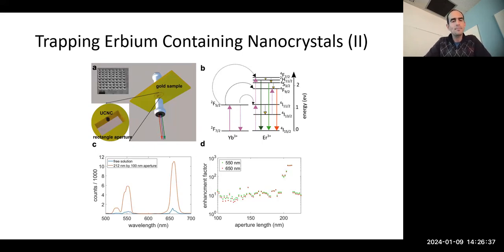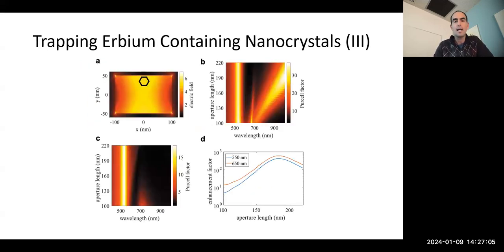Why was it exciting? We realized that we have about 400 of these emitters inside these nanocrystals, and we can observe the upconversion from just one nanocrystal. So if we manage to enhance that emission by 400 times, you realize quickly that you could probably observe the emission from just a single emitter. We've got enough sensitivity in our system to observe a single emitter.